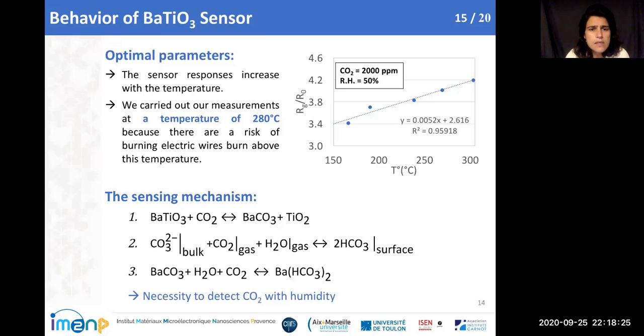If we want to optimize our parameters, we can see here on this graph that the sensor response increases linearly when you increase the temperature. However, we can't go above 280 degrees because we have a risk of burning electric wires inside our chamber. So we decided to stay at this value to make our measurements. And for the sensing mechanism, we can see here the equations where we can find that we need water, we need humidity, to have the carbonation of the carbon dioxide.